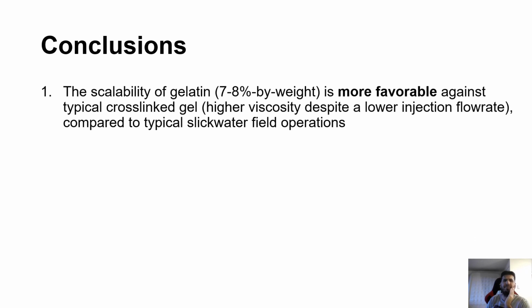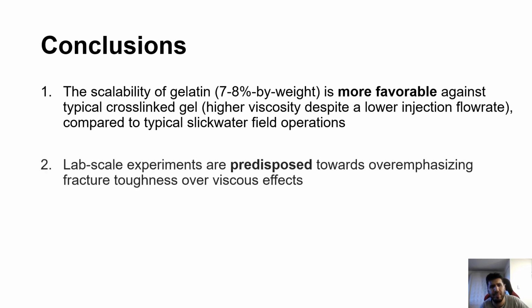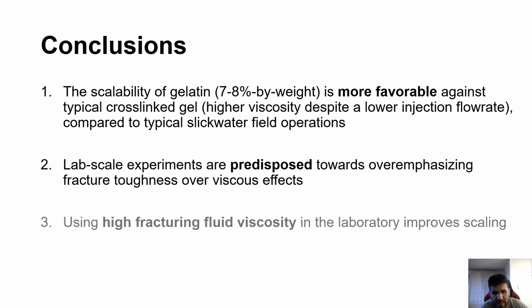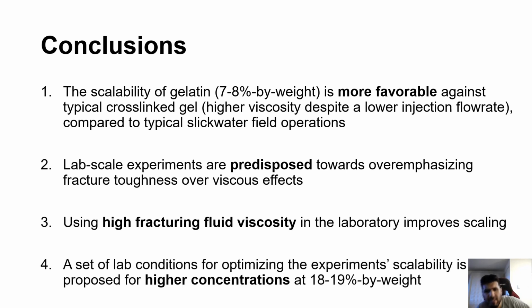In conclusion, the scalability of gelatin for the conditions used in my master's work is more favorable against typical cross-linked gel fracture treatment, which has higher fracturing fluid viscosity, despite a lower injection flow rate compared to a typical slickwater field operation. The lab scale experiments are predisposed towards overemphasizing fracture toughness over viscous effects. Using a high fracturing fluid viscosity in the laboratory improves scaling, and a set of lab scale conditions is proposed for optimizing experiment scalability compared to the field operations at a higher gelatin concentration of 18 to 19% by weight.